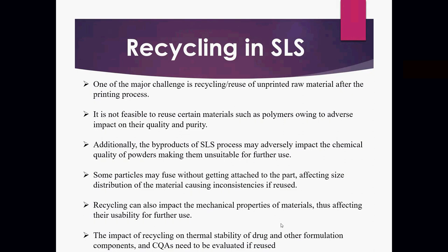So this is one of the major challenges we are studying now in SLS, whether you can use this unprinted raw material after the printing or not. It's not feasible to reuse certain materials such as polymers owing to adverse impact on their quality and purity, like the byproducts of the SLS process may adversely impact the chemical quality of powders, making them unsuitable for further use. Since it's already exposed to heat, exposed to laser, you can't decide whether this powder is completely 100% like the fresh powder or not. So you can't recycle this one again, or it might affect your